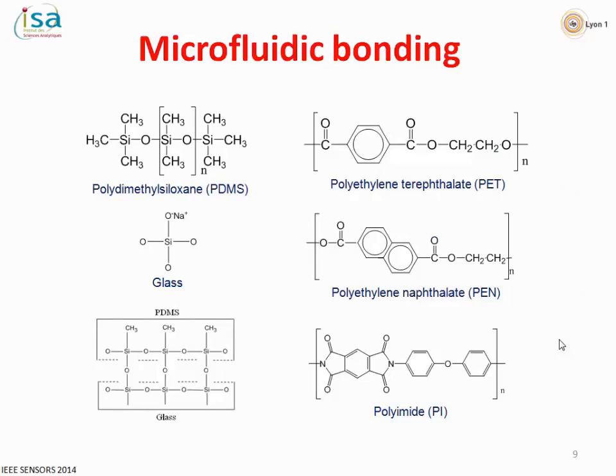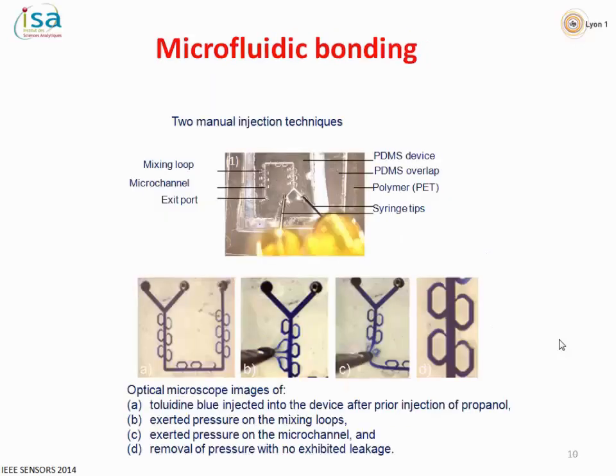Here I show you that all these substrates have been tested, and we tested glass because it was the reference for us, in order to see if we have some leakage and so on. Well, this is the prototype, as we can see here. These are the loops, and this is PET as a substrate, PDMS, and after that we start to inject two kinds of liquid in order to see if we are able to mix inside the loops.